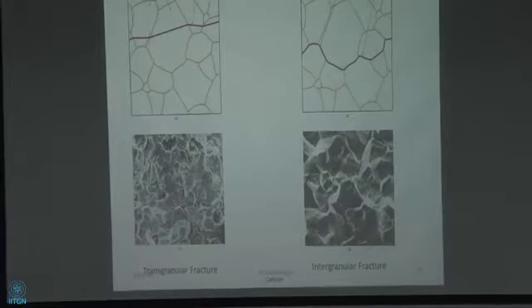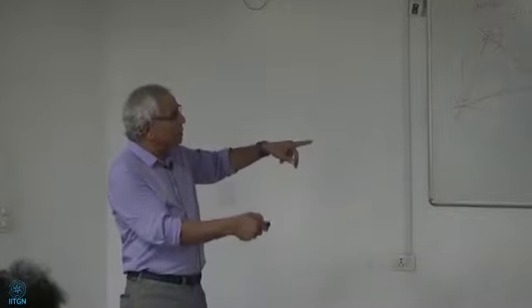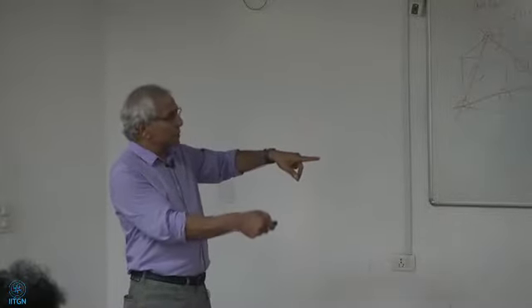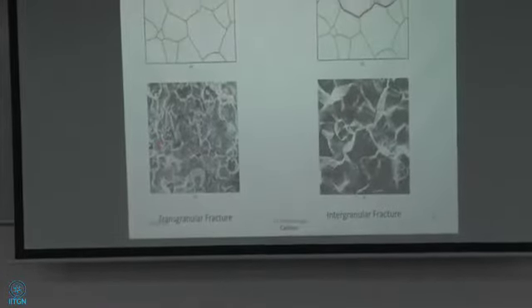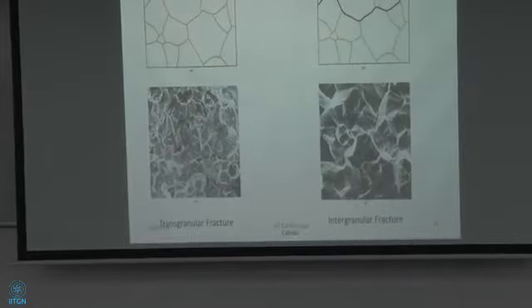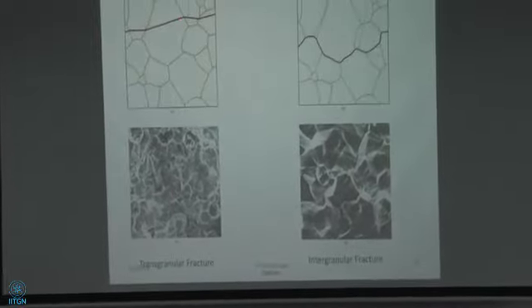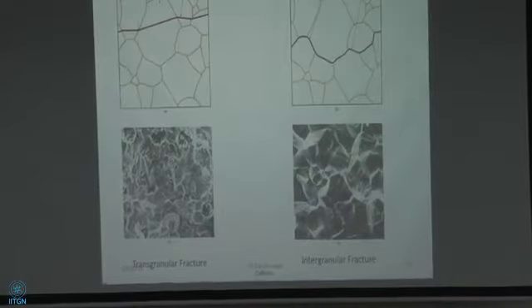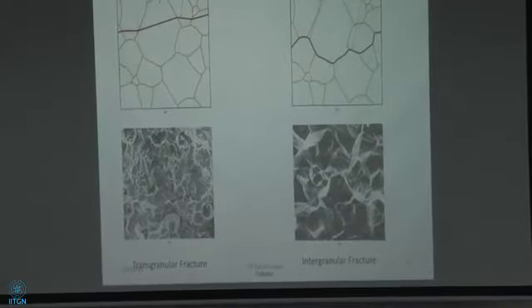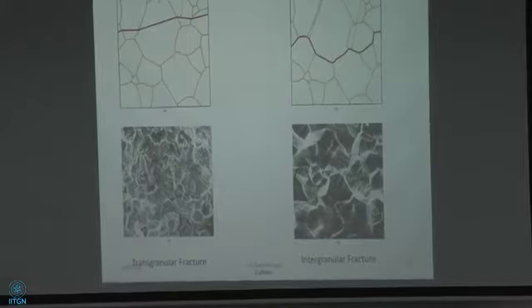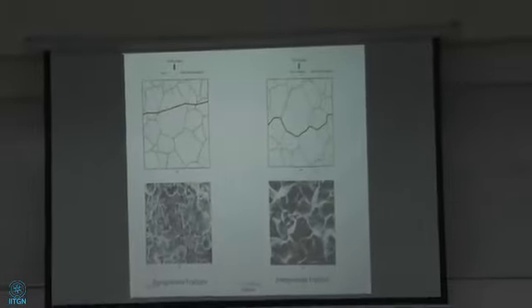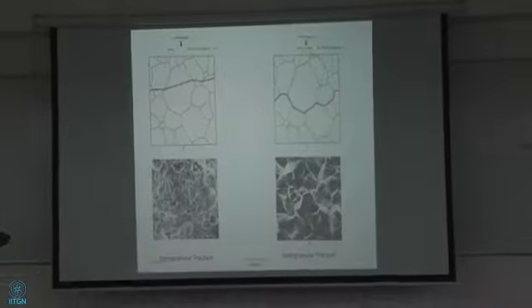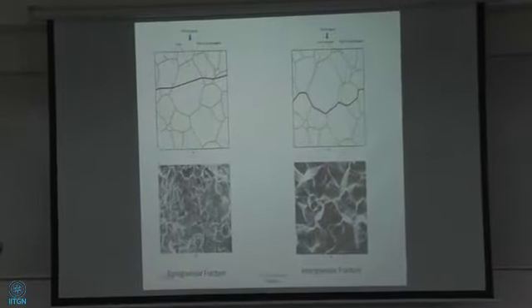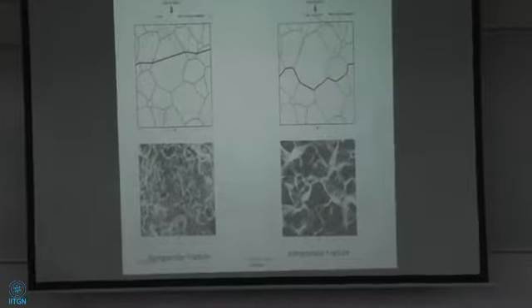So the ductile fracture is more transgranular fracture. So the brittle fracture that we just talked about, cleavage, this is a brittle fracture mode, cleavage. This is a scanning electron microscope picture. But you see, it's a transgranular fracture. Even though it is a low energy fracture, it's a transgranular fracture. It means the crack is propagating in between the grains and not along the grain boundaries. Okay? So this is an intergranular fracture which is propagating along the grain boundaries.